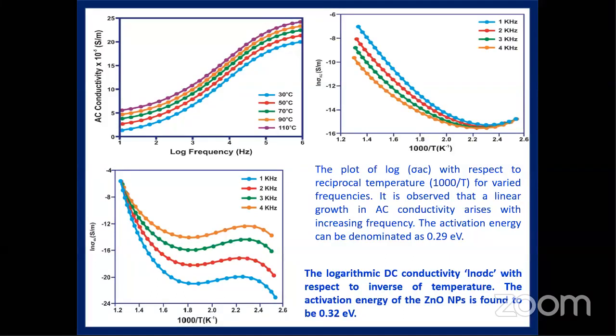Then you can see there are two graphs here, ln sigma AC with respect to 1000 by T. This is the Arrhenius plot. From this plot, we can calculate the activation energy. From the AC conductivity Arrhenius plot, the activation energy was calculated to be 0.29 electron volt. Similarly, for the DC conductivity, the activation energy was calculated to be 0.32 electron volt.